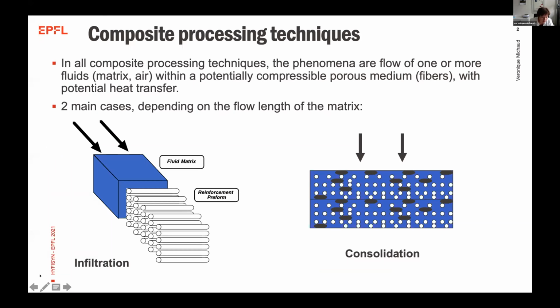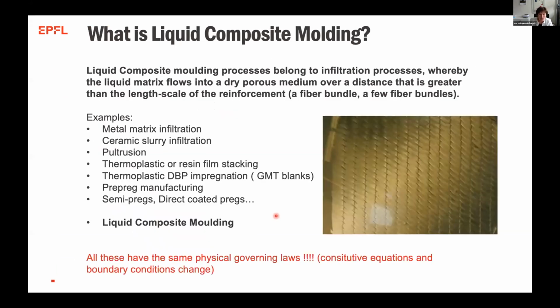So what are composite processing techniques? Typically you know a lot about pre-preg production because you've heard Alexios presenting, and pre-preg production really goes more into this idea of consolidation, where you have pre-mixed already in some pre-impregnation phase the fibers and the matrix, and then during fabrication of the composite, you just press, you consolidate, you remove porosity, and you get the final part. There are some other processes which are more infiltration processes, where you have the reinforcement preform that is dry. The fluid matrix you push under pressure or not, and then you get the composite at the end. So liquid composite molding really fits into the second category.